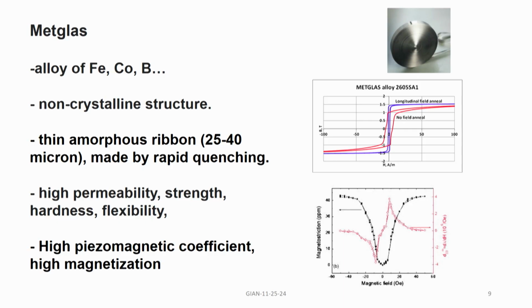Metglass is another material with very high permeability. It can be as high as 100,000. So, Metglass is made by what is called rapid quenching. They mix all these metals, iron, cobalt and boron, to make a molten flux, and it is dropped onto a spinning wheel at very high speed. So, the ribbon they pull out is amorphous, it is not crystalline, it has very high permeability and pretty good magnetostriction. It is usually in the form of a ribbon, 25 micron in thickness. You can buy a spool of it.